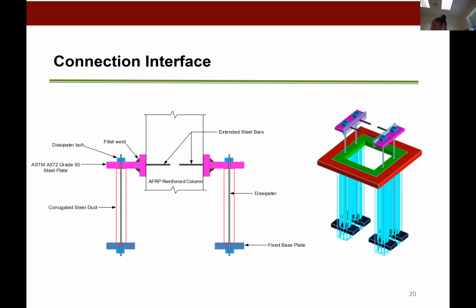We have a footing that has a square column and a head block that we're actually using to attach the actuators. So the main objective for the rocking connection is to look at the stability of the column under axial load as well as bending and any possibility of failure of the columns along the cross section above the column foundation interface. So what we see here, we have extended steel bars within the concrete column, fillet welds around the steel plates that then are attached to a core, attached to the actual energy dissipators that are within a corrugated duct that run through the foundation of the system.